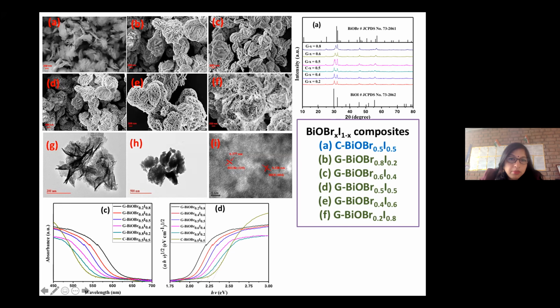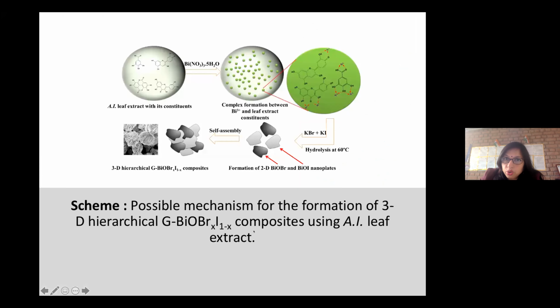Now here the UV-DRS studies were done, and the band gap in the case of the Br 0.2 and I 0.8 sample was the minimum, because I has the lower band gap. So Br was only 20%, and 80% was I. So it is helping to solve the recombination problem, enhancing the activity and lowering the band gap.